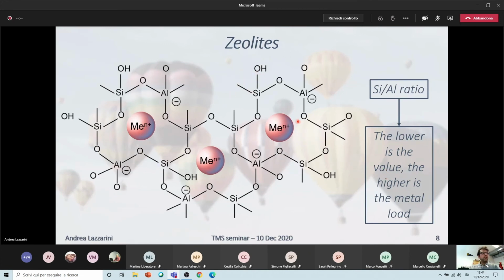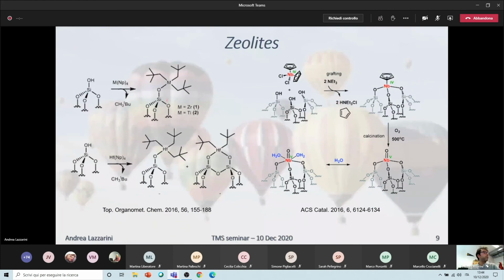But this is not the only possibility to introduce a functionality inside the zeolite. Being a silicate, a catalyst can be produced by grafting a metal organic moiety onto the surface of the zeolite by different chemical reactions, by surface organometallic chemistry. They can be grafted and anchored to produce a heterogeneous catalyst where the metallic phase that is loaded onto the surface of the zeolite can be the active phase. And they can also be bifunctional catalysts, in which you can have a metal loading outside that is performing redox chemistry, and you can still have an acid catalyst by continuing to carry the protons inside the lattice of the zeolite.